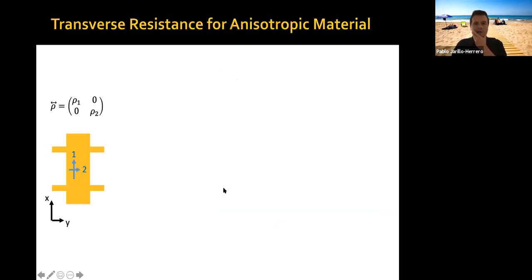Now you may wonder, how can it be that we have finite Hall resistance if we have zero magnetic field? Well, this is something that can happen when you have an anisotropic material. So we have a Hall bar. Let's imagine we have this material which is anisotropic, and you have different resistivity along the X direction and along the Y direction. Your resistivity tensor has these values rho one and rho two in the X and Y direction. If your axes of anisotropy are aligned to your Hall bar axes, then you would expect to measure zero Rxy, zero transverse resistance in this device.